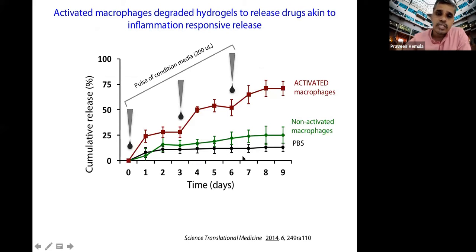When gels were exposed to these conditioned media, as you can see, when exposed to the non-activated, meaning non-inflammatory, conditioned media, you don't see much release of the drug. This is as good as buffer, right? Whereas when you expose to the conditioned media taken from the activated macrophages, you can see the release of the drug. Not only that, whenever you give a fresh pulse of activated conditioned media, you see they release the drug in a responsive manner. Which is clearly suggesting that indeed this material has the ability to respond to inflammation and release the drug in a dose responsive manner.